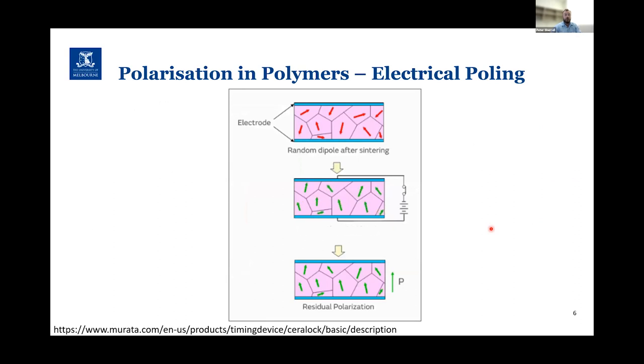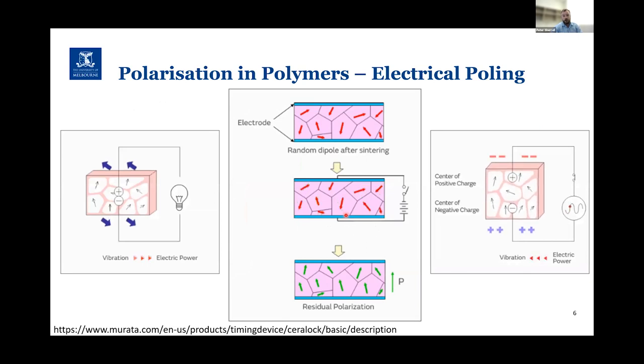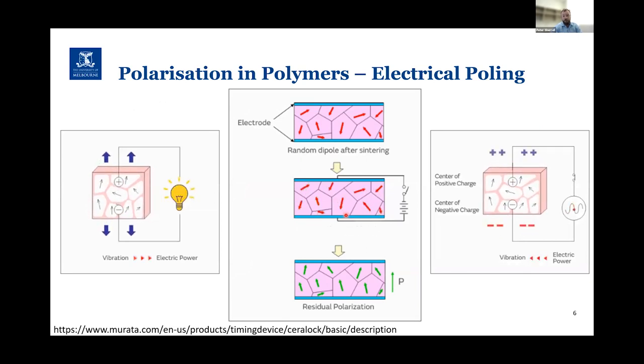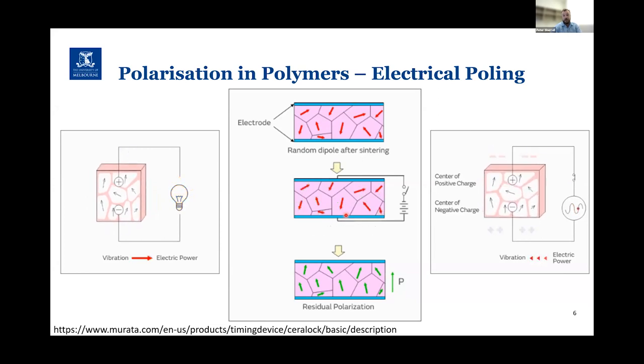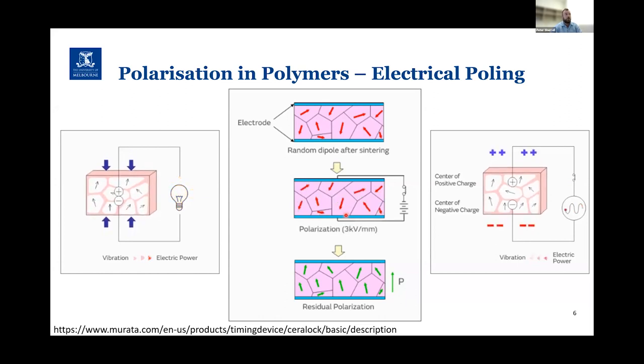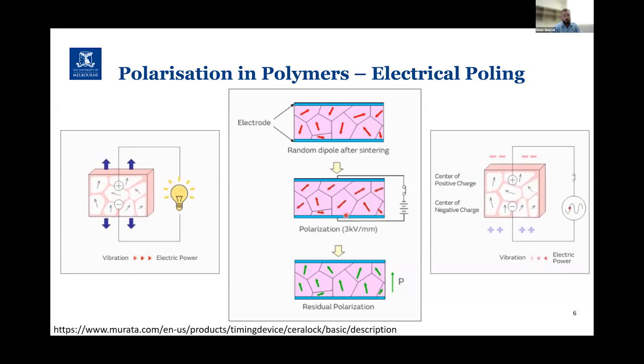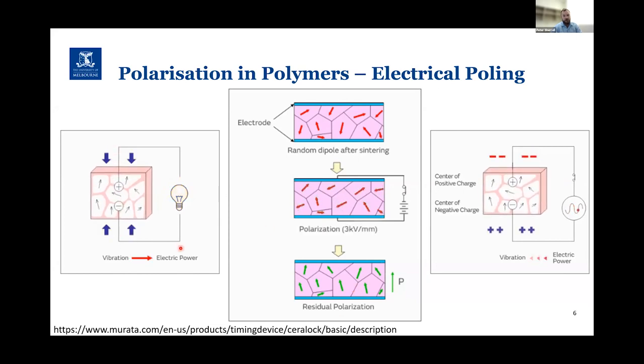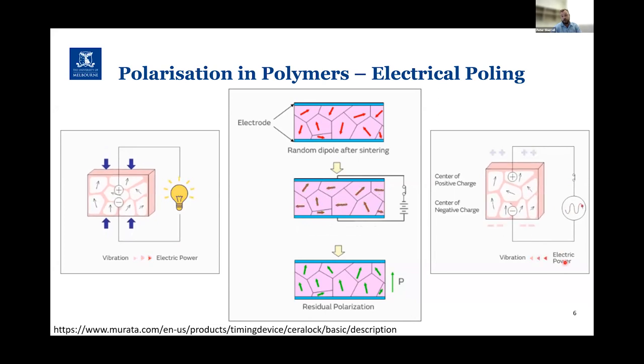So how people have traditionally overcome this is they put two electrodes on the top and bottom of a polymer film and flick a switch and pump through anywhere up to 100 megavolts per meter of electric field across your polymer film. And this causes all these polymer crystallites to twist and align in a single direction. The problem with this is no one wants to spend 100 megavolts per meter to make a piezoelectric energy harvester. You're never going to save that energy over the lifetime of the device. So it's just pointless, and it's really limited anyone trying to move forward with this sort of technology on a really wide-ranging, large-scale system. But regardless, if you do this, you have this polarized sample, you can apply a stress and get electric power out, or alternatively, you can apply an electric field and cause it to vibrate.